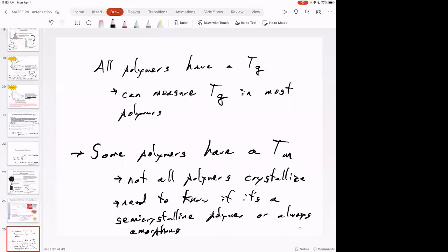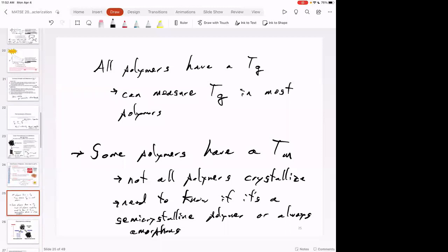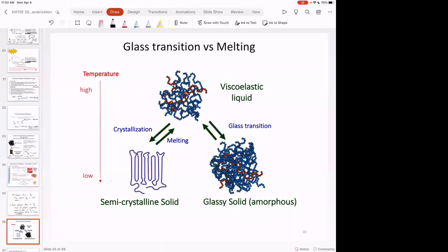But polyethylene terephthalate has really, really small crystals. It's clear, the crystals are very small, and the crystals stop oxygen from permeating through PET. That's why it's a good material for carbonated beverages, water, all of that sort of stuff. So looking at the polymer is one indication, but PET is the counterexample where the crystals are just really small, you can't see them. So you'll learn more stuff like that as we go on, but like I said, it's really useful to have an idea of what's happening with semicrystalline polymers and amorphous polymers.